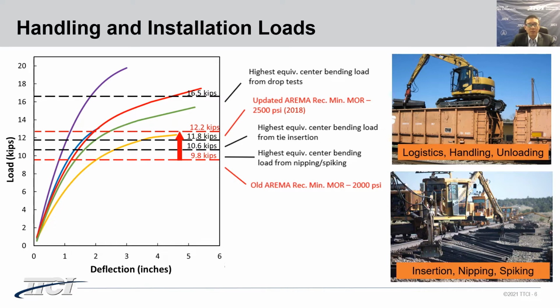As we can see in the plot, maximum bending stresses in composite ties during insertion, nipping, and spiking were higher than the old AREMA recommended minimum MOR. Dropping composite ties may generate even higher bending stresses. Based on the results, an AREMA recommended minimum MOR of 2500 psi was proposed, and it has been updated in the AREMA manual in 2018.